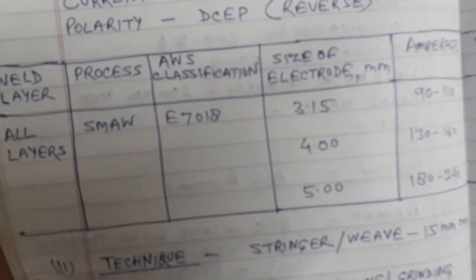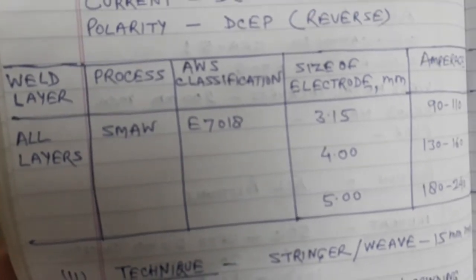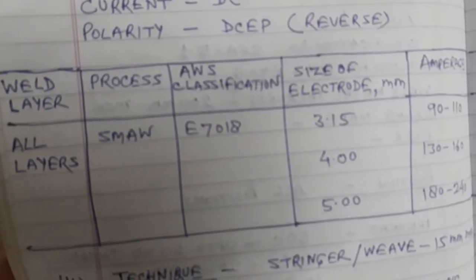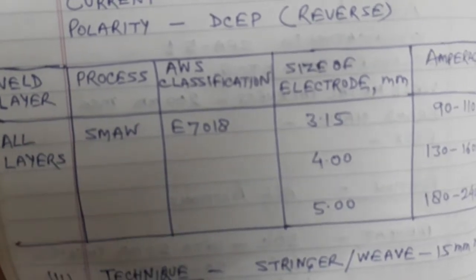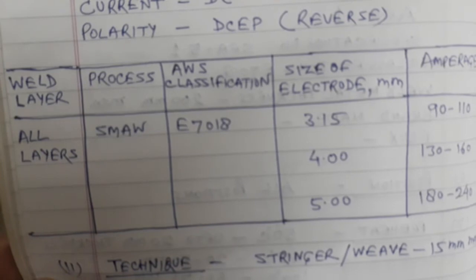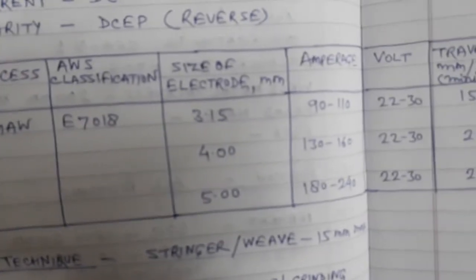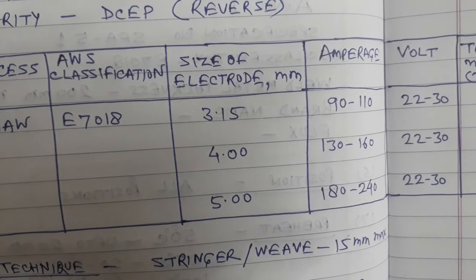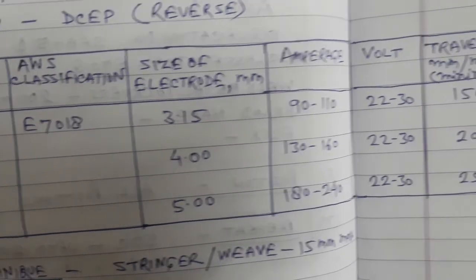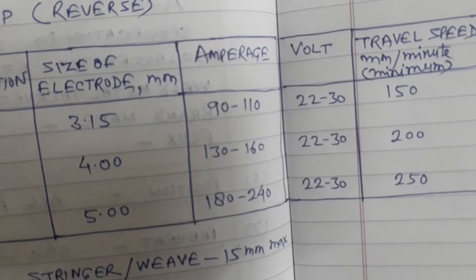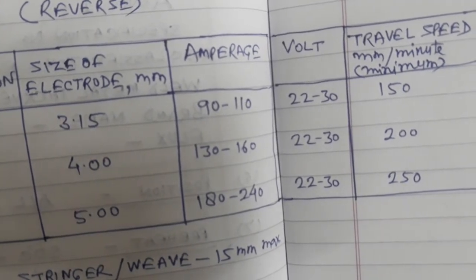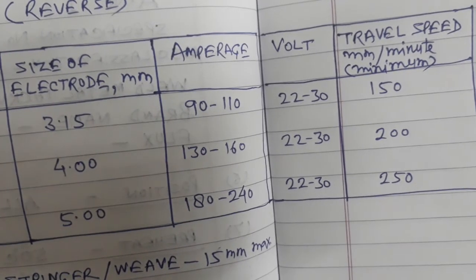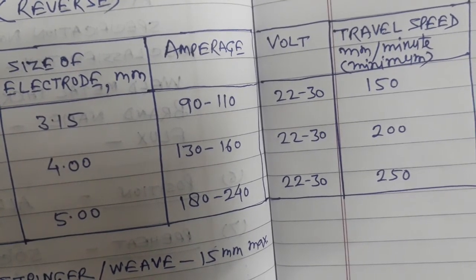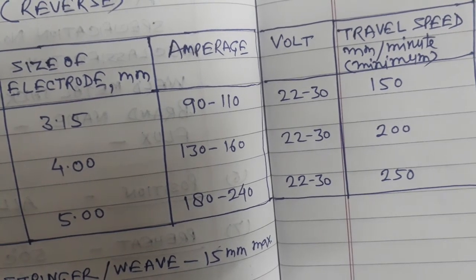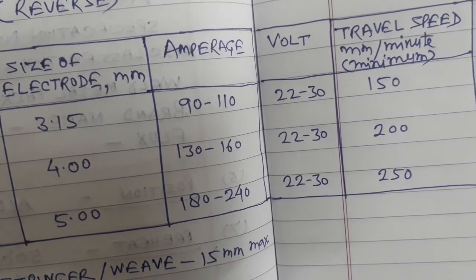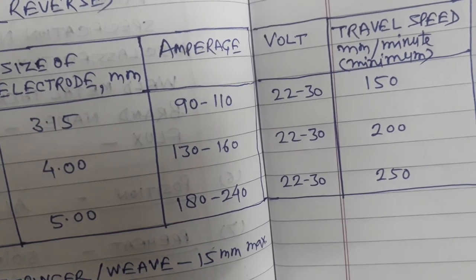So you can see for all layers the process is SMAW, and AWS classification is E7018. Size of electrode 3.15 mm, amperage 90 to 110, voltage 22 to 30, and travel speed 150 mm per minute minimum. That means a welder has to weld at least 150 mm in a minute.